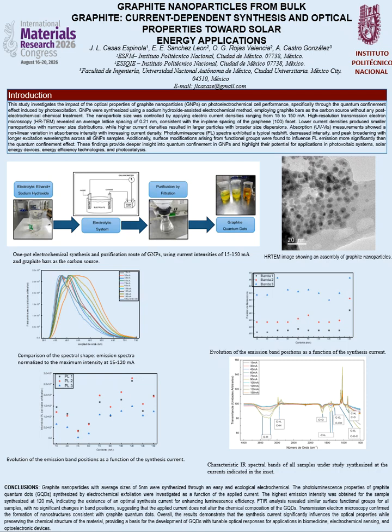The spectra revealed the presence of the same functional groups in all the samples, such as C-O stretching vibrations, 1078 cm^-1, carboxylate groups and/or C-H bending vibrations, 1387 cm^-1, aliphatic CH3/CH2 stretching vibrations, 2970 to 2820 cm^-1, and two absorption bands centered at 3260 cm^-1 and 3446 cm^-1 were assigned to O-H stretching vibrations associated with strongly hydrogen-bonded hydroxyl species and surface hydroxyl groups, respectively.